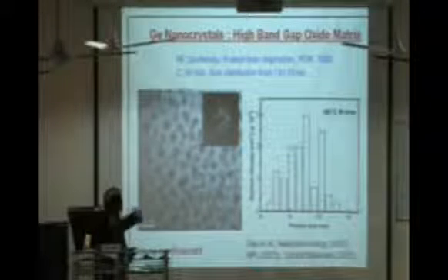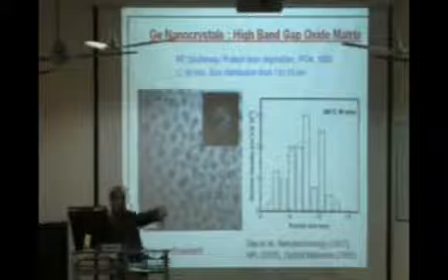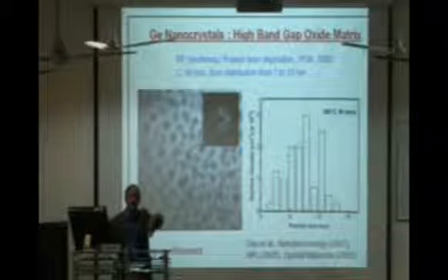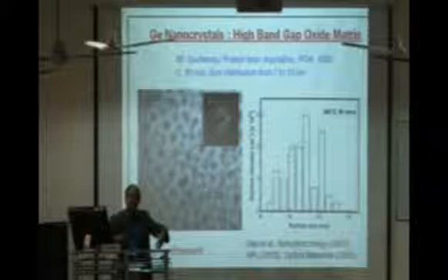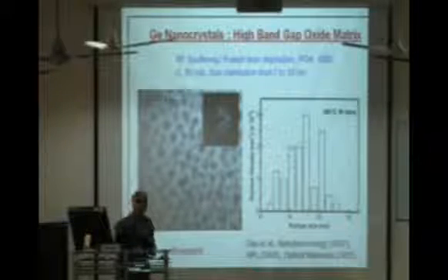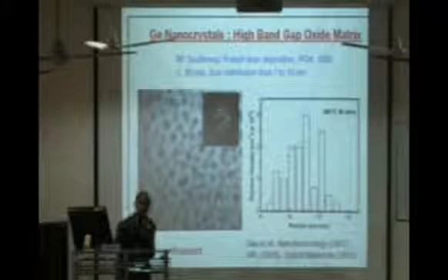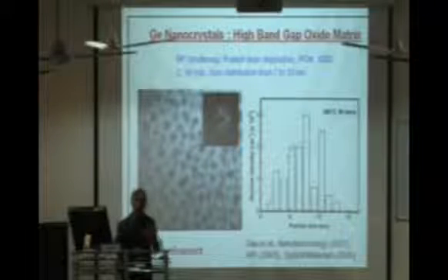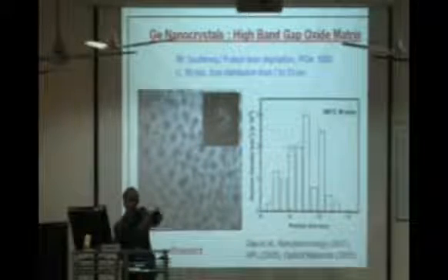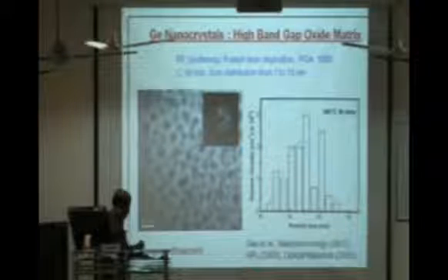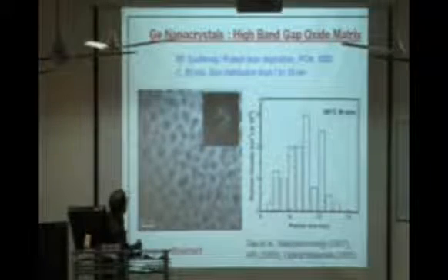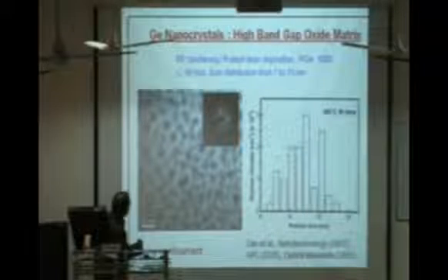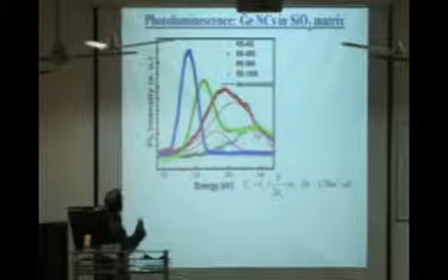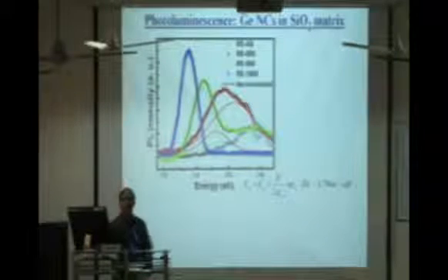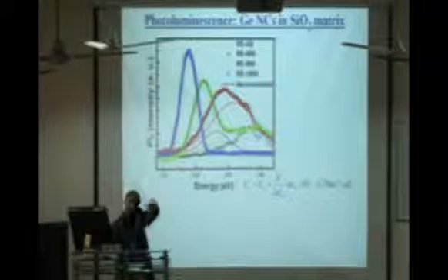Okay, so these quantum dots can also be embedded in a high band gap matrix, like an oxide matrix. In fact, these quantum dots can be used for solar cell applications and many other photonic devices. But one of the main problems is how to embed them in a defined kind of material. Many other groups have shown that these quantum dots can be embedded in a high band gap silicon dioxide matrix. And when you put them in the silicon dioxide matrix, the photoluminescence intensity is very, very strong, and that can be achievable at room temperature.